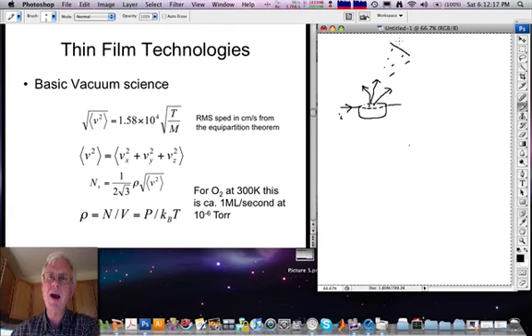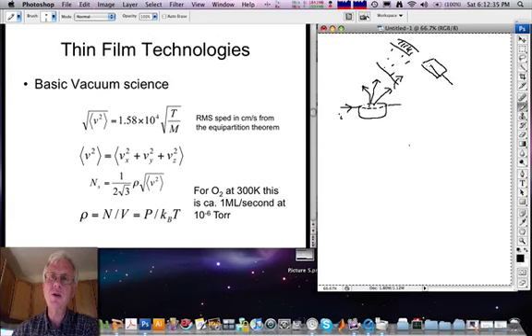Typically one might have behind the target a heater to control the temperature of the target, and we'll see why that's important in a moment. One may have a shutter here to control the time exposure, and then typically somewhere close by, a thickness monitor, which is a quartz crystal whose frequency changes as metal atoms deposit on it.